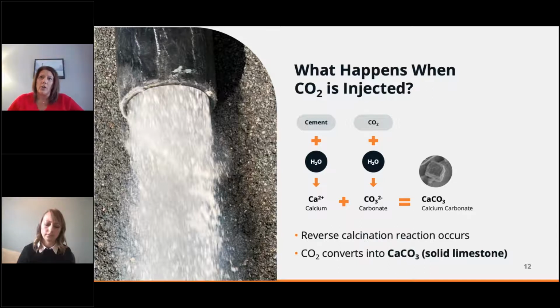Now, carbonated concrete is created through what's called the reverse calcination reaction. Calcination involves breaking that calcium carbonate mineral apart during the initial cement manufacturing process, where that CO2 gets released and becomes a greenhouse gas emission. What we're doing with reverse calcination is putting that calcium carbonate mineral back together. When we're injecting CO2 into the concrete, that CO2 is almost like a magnetic attraction to the calcium oxide in the cement. So those two molecules get back together in their natural state, which is a solid calcium carbonate, or a limestone mineral.